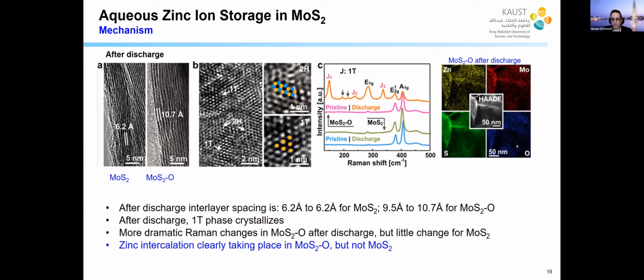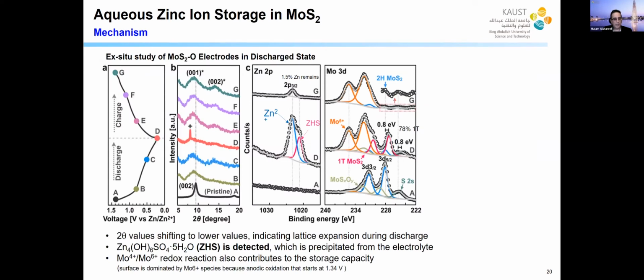You look at the EDS, and you will see actually the sulfur, the zinc, and the moly and the oxygen. This shows that after discharge, again, discharge means the zinc going into the cathode, we have uniform zinc throughout. So that means we have successfully intercalated zinc in the electrode using the oxygen substituted molysulfide. You can, again, study in more detail and see what really happens.